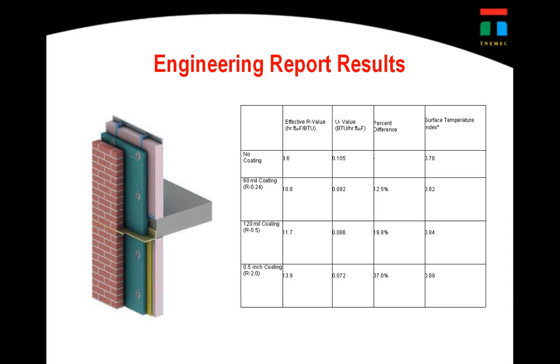As far as you know, an oil-based or asphaltic material doesn't corrode the coating? No, it shouldn't. It's totally water-based in that respect. So we won't have any corrosion effect that takes place with this. This is basically a single component material that is spray applied, and once it gets cured down, it's relatively hard,